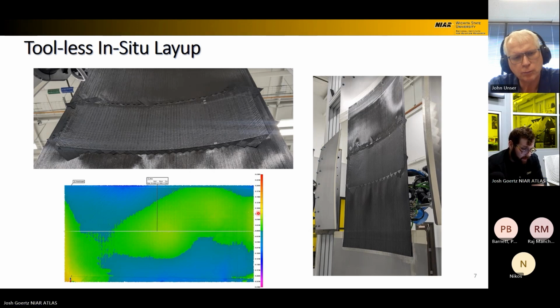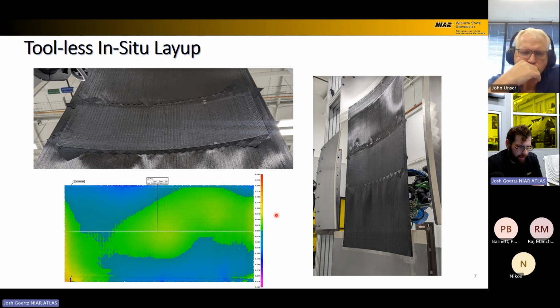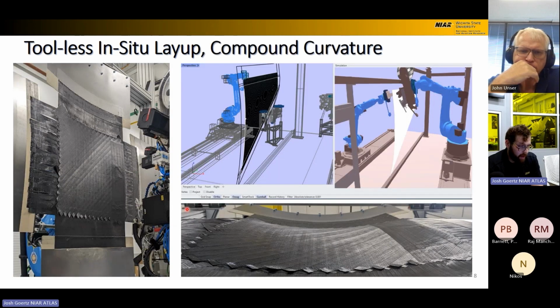And then when fitted to a perfect cylinder, this color chart shows the deformation in and out of plane, ranging about plus or minus 70 thou with the current process. So that was a single curvature part. And then from there, we moved on to the double curvature panel that I was describing before, which is the convex curve swept along the concave curve.